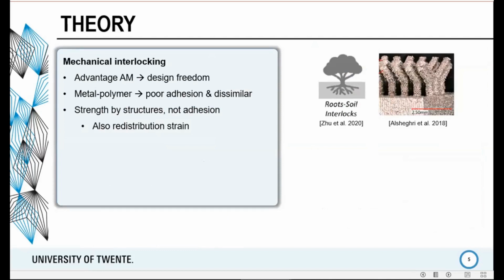Now, what is mechanical interlocking? Mechanical interlocking is the concept where, instead of adhesion, you use the shape of both of your materials to create some interlocking structure. So let's say you have material A, material B, you create a shape so that they simply cannot be moved apart without tearing them, without breaking them. And additive manufacturing is really interesting for this because of the design freedom that you have. So one example, which is from the literature, is printing these metal tree root kind of structures, which extend into a polymer, which you can mold around it. So in this way, you really have a shape that locks into another shape.